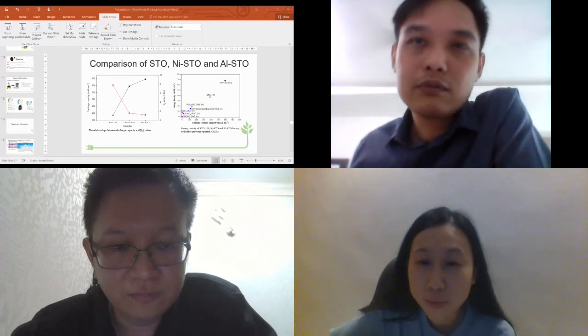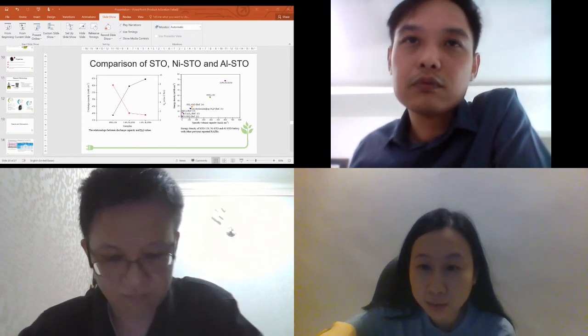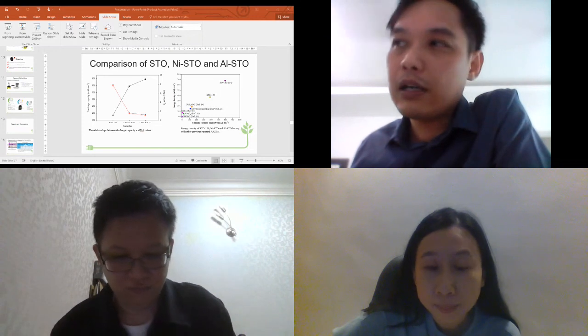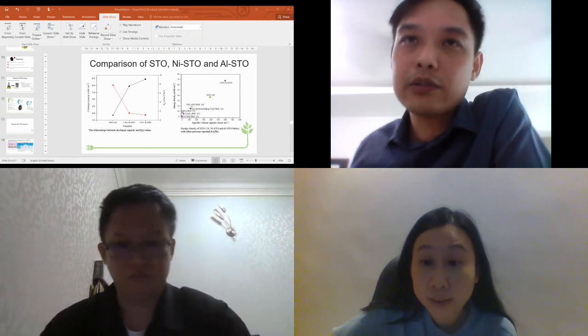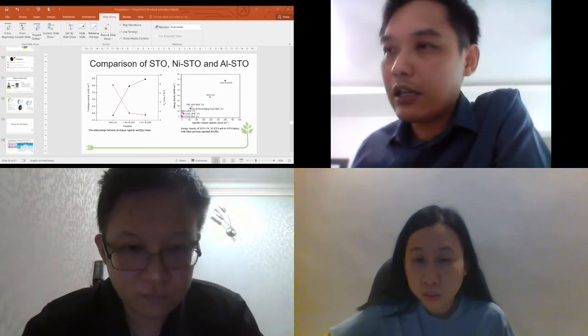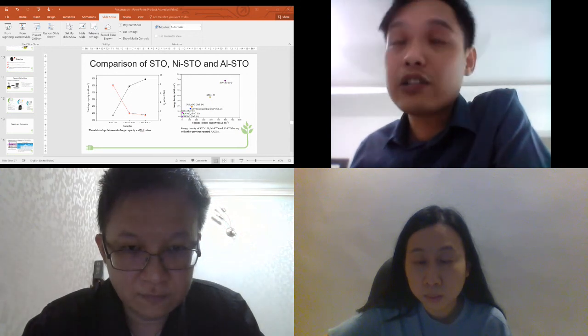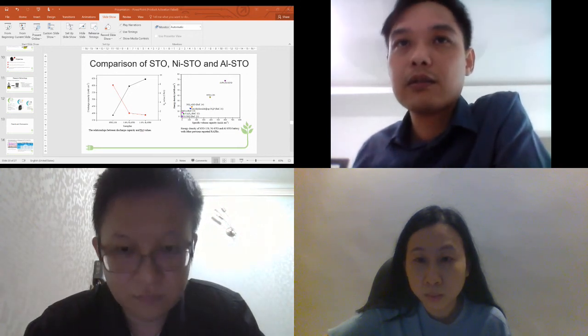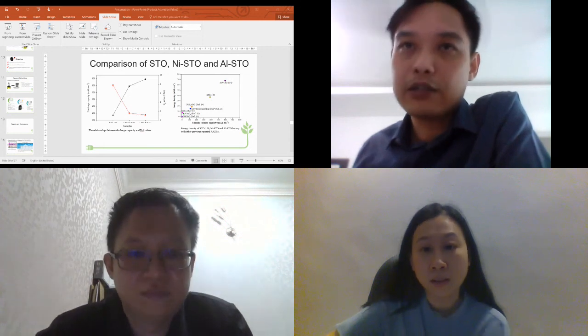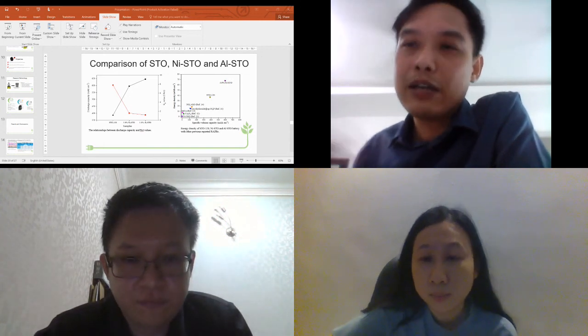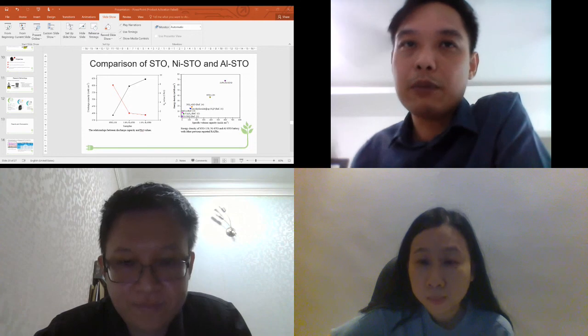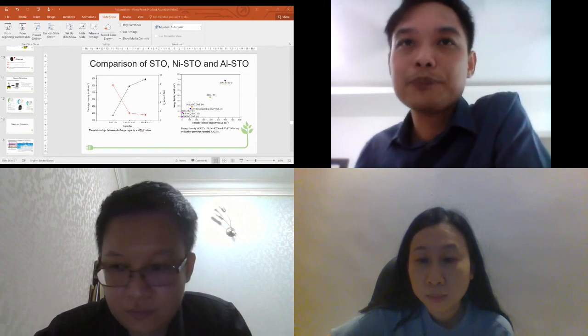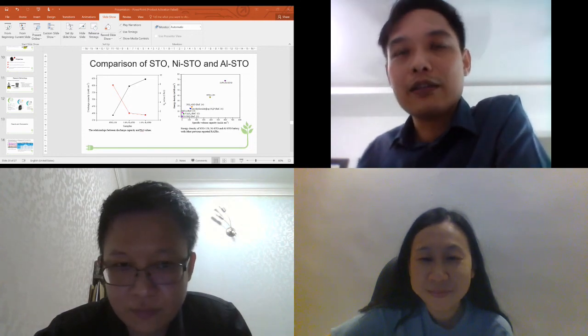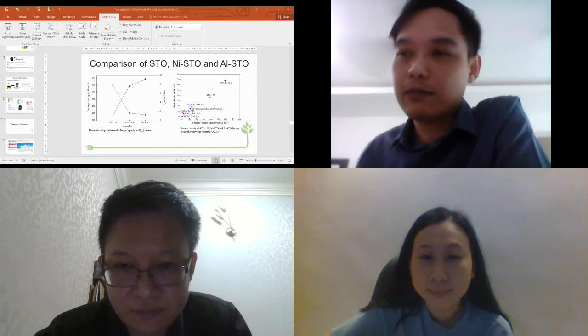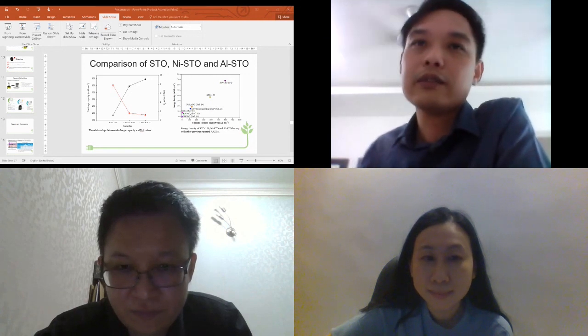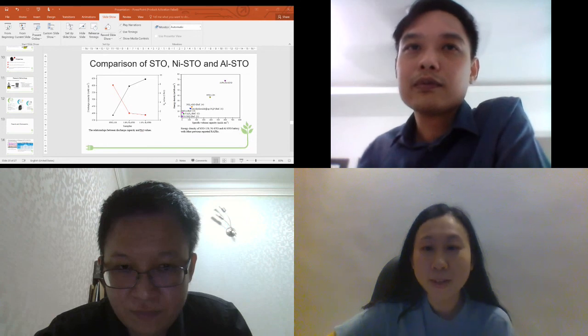Have you tried charge and discharge? How many cycles? Yeah, we tried about 100 cycles, only 100 cycles. But we did not find any reduction in the charge capacity up to 100 cycles. That's very good. It's very common in batteries to try 50 to 100 cycles, or people sometimes go for 1,000. It's a very common practice in batteries that people try 50, 100 cycles. Yeah, thank you, Dr. Chuan.